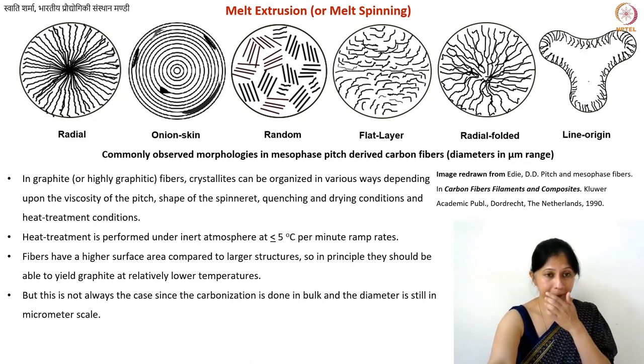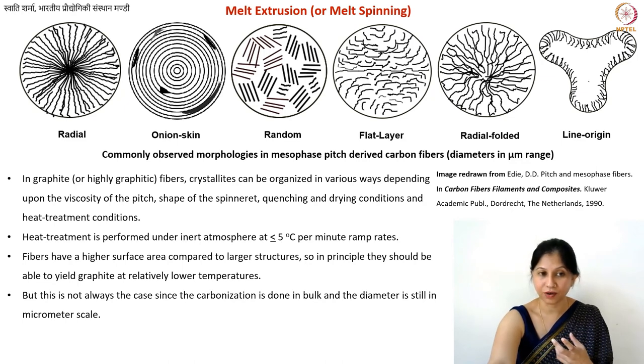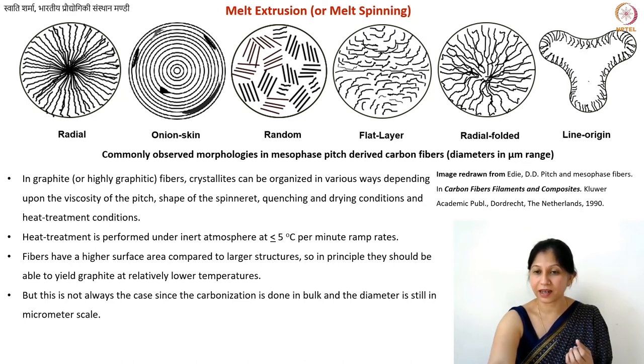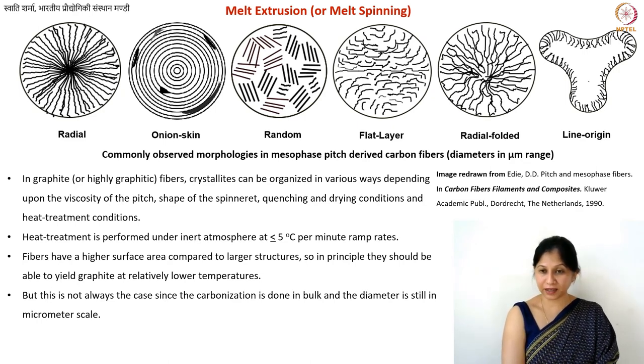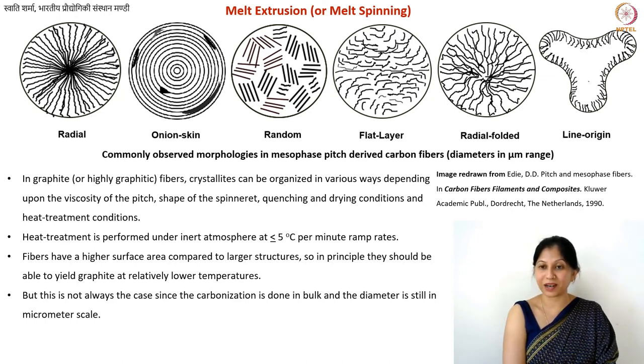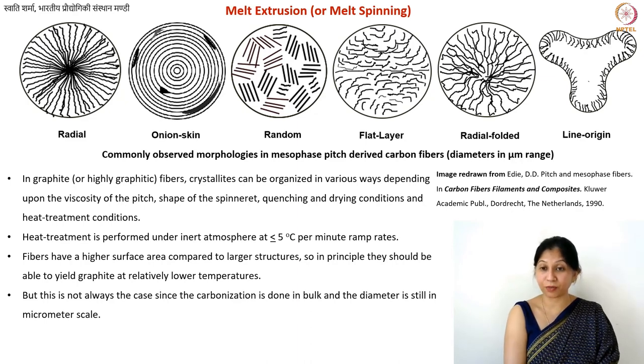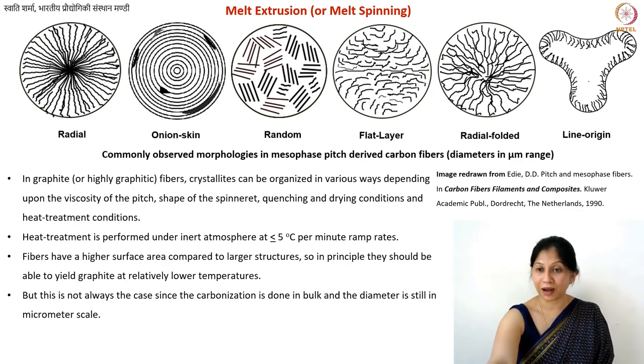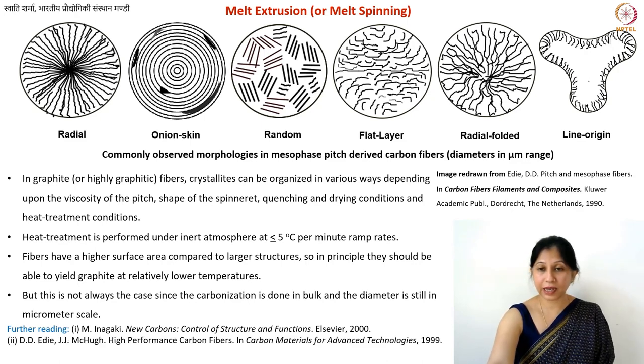Fibers can be made at micro or nano scale. During heat treatment, slightly lower temperatures may be used since byproducts and defects anneal out more easily due to high surface area. In the micro scale, this surface area effect is not very strong. For nano scale fibers below 50 nm diameter, the carbonization mechanism becomes different and more graphitization can occur at lower temperatures. For micro scale structures, this effect is present compared to bulk but not prominent enough to drastically reduce heat treatment temperature.